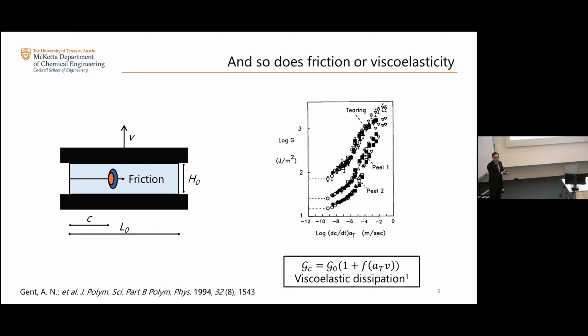And you have these chains that can basically slide against each other. You have a friction coefficient. We call that viscoelasticity sometimes. And effectively ahead of the crack tip, you can have molecular damage, but actually a lot of the contributions also come from viscoelasticity. And the consequence of that is a fairly well-known observation, that as you fracture your material at different velocities or at different temperatures, you can actually get differences in the fracture energy because your system is more or less viscoelastic.